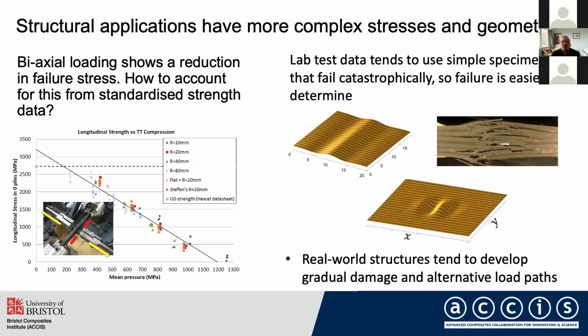Going even further to more structural level loading, where we are looking at more complex geometry and stress states. We measure strength, as Michael and Federico suggested, in a unidirectional stress state, but at a structural level, we are more likely to encounter multi-axial loading. And the bottom left chart shows some tests we did where we have a specimen loaded in tension, but with some applied highly localized compressive stresses.